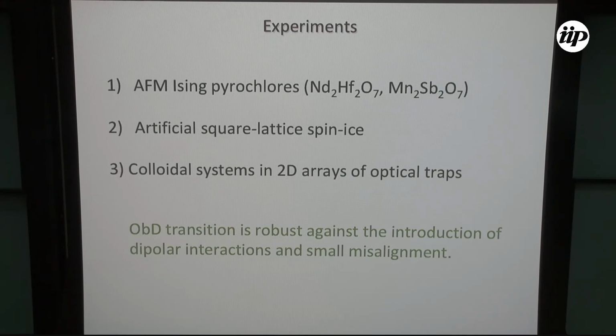As I said, this is still work in progress. We know that there are at least these two candidates that are supposed to be antiferromagnetic Ising pyrochlores. The problem is that because this is a very low temperature phenomenon, you need to have very clean antiferromagnetic pyrochlores. If you have additional interactions, those interactions tend to mess with this picture and you don't see anything.